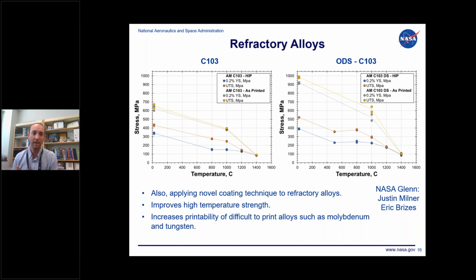This is some early work that my colleagues Justin Milner and Eric Brizes have been doing on C103 and ODS C103. What they've been able to find is that when we incorporate these dispersoids into C103, you're able to significantly improve its strength compared to non-ODS versions. If we look at these room temperature curves from left to right, look at those yellow dots, you can see almost a 40% increase in strength.